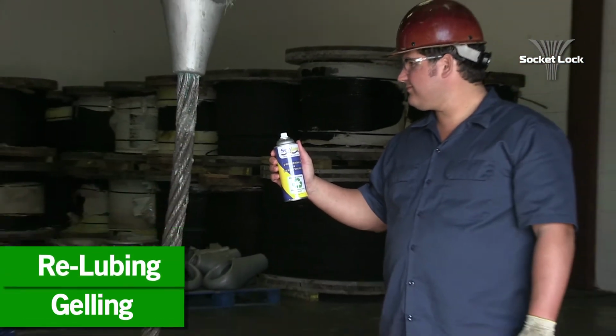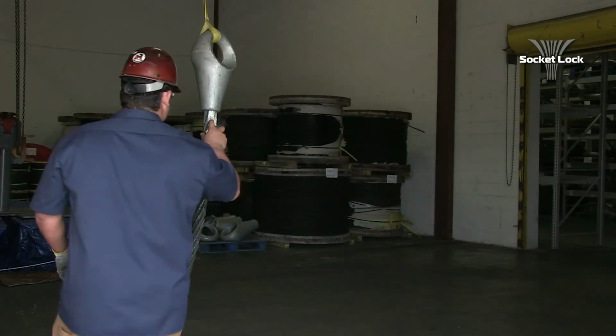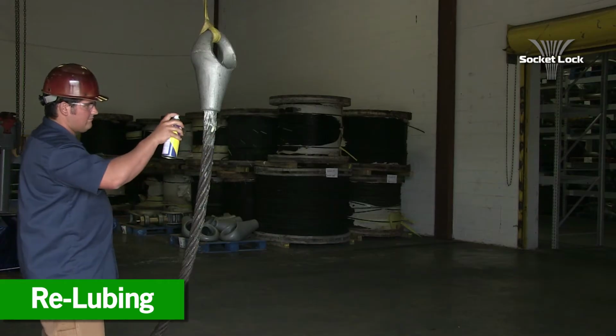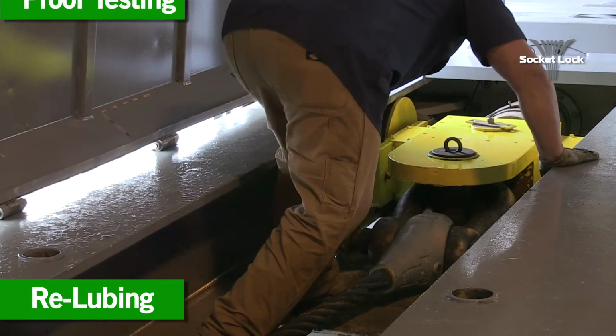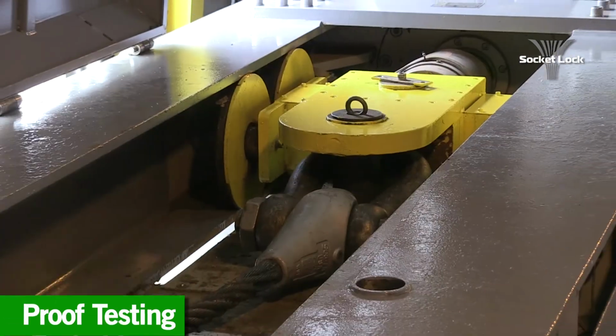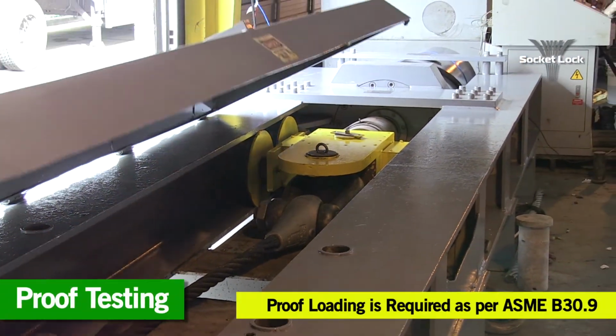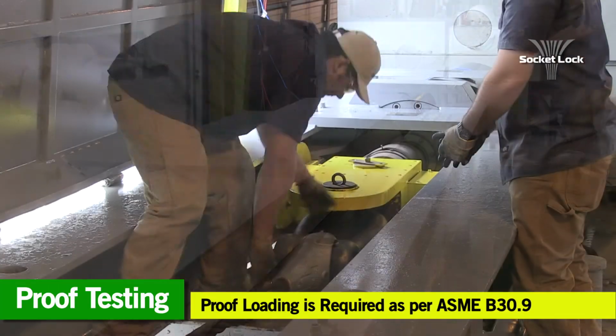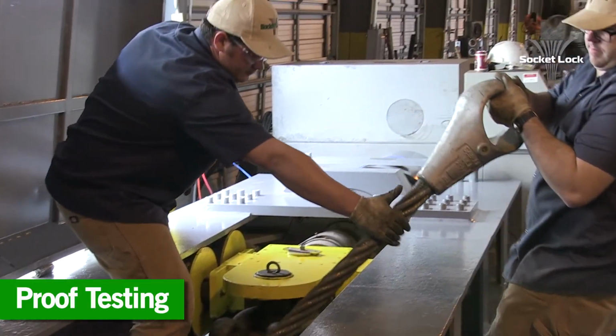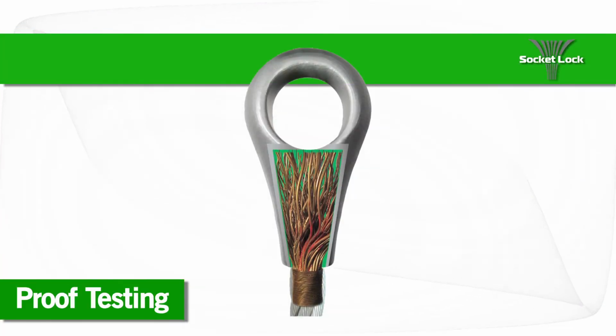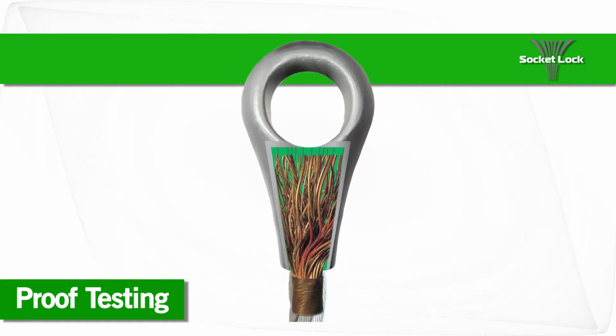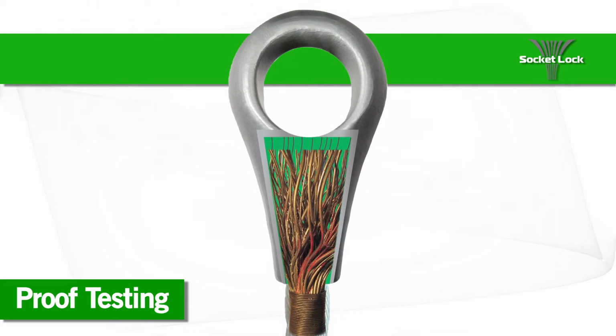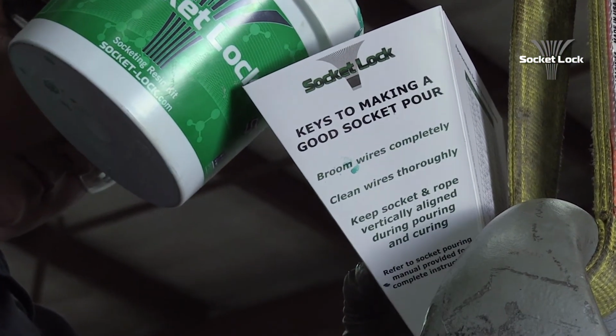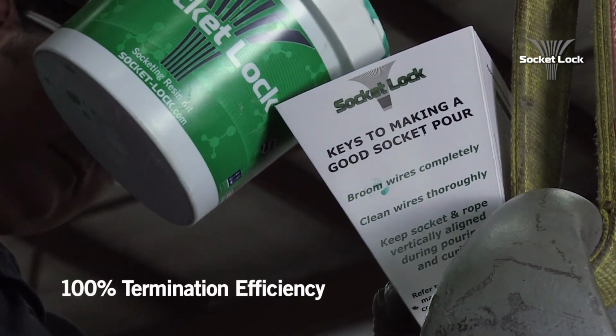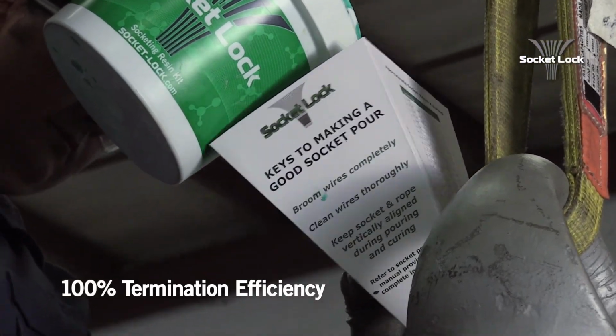After the resin has cured, relubricate the wire rope to replace any lubricant that may have been removed during the cleaning process. It is recommended to proof load the assembly to twice the working load limit prior to putting the assembly into service, per ASME B30.9. Proof loading will seat the cone into the socket, removing the gap found between the socket wall and the resin cone, in addition to wedging the cone tightly into the socket and preventing it from popping out. When all of the procedures are properly followed, Socket Lock will provide 100% termination efficiency.